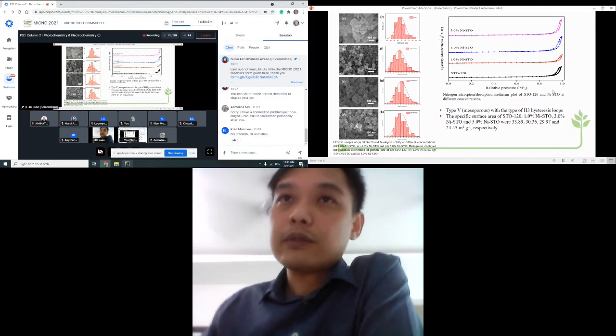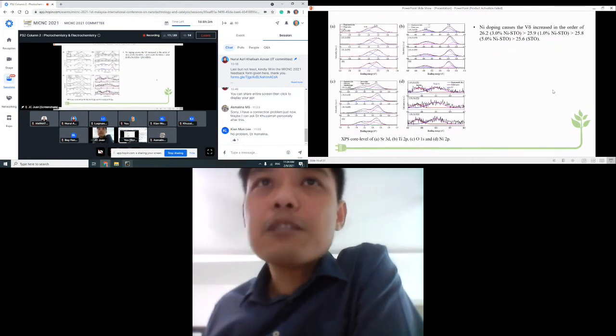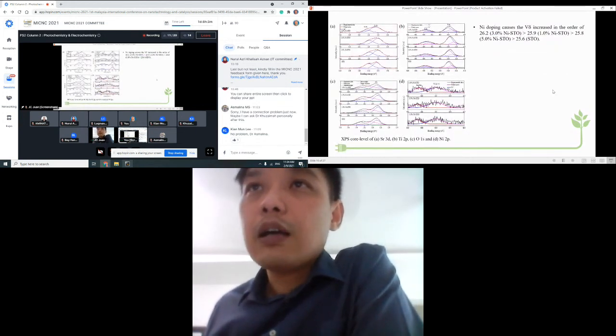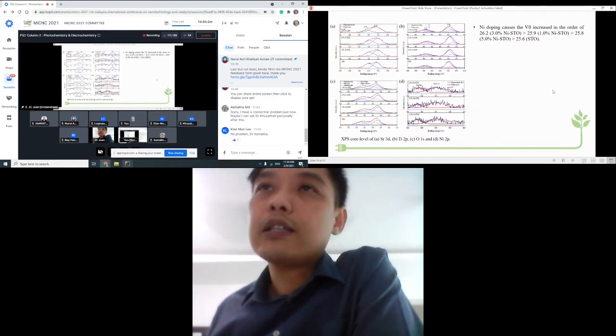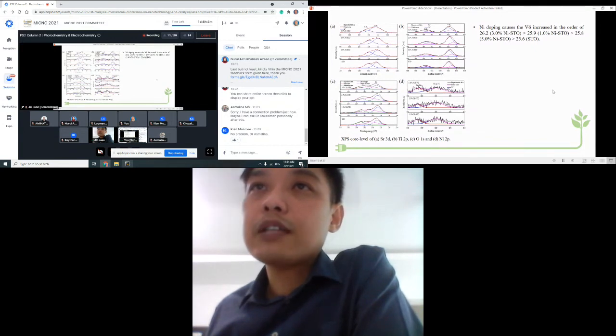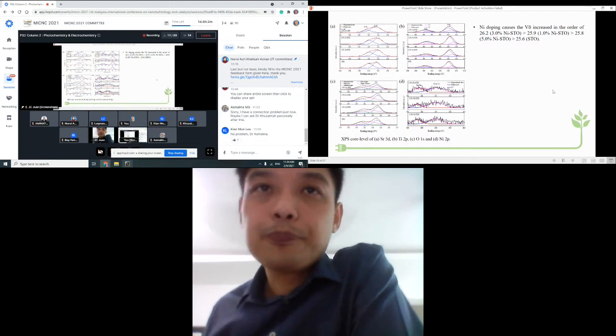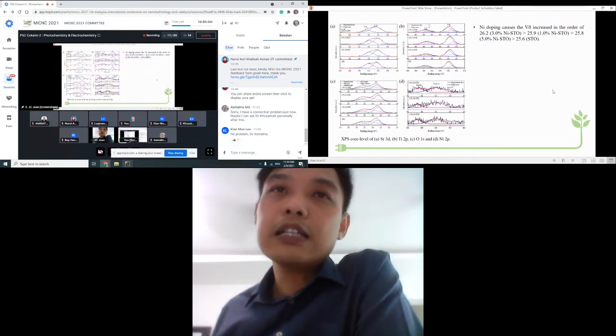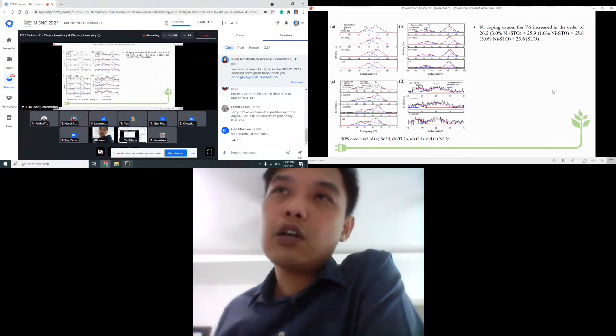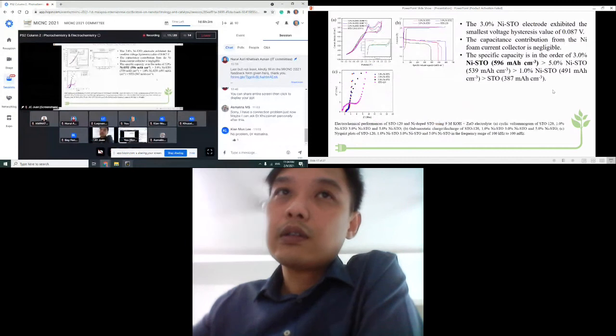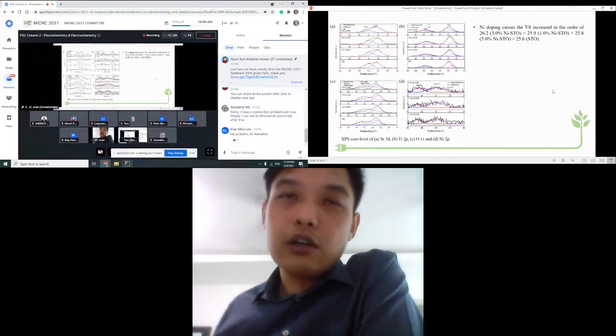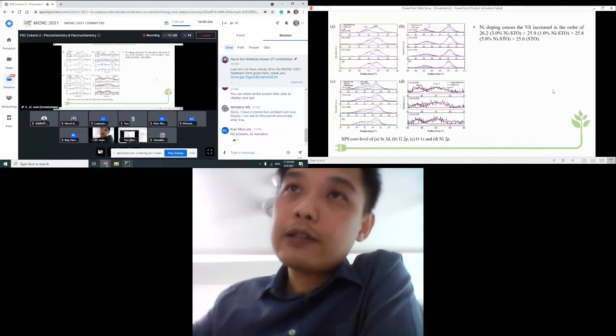From XPS, this is very important data. The nickel doping caused the oxygen vacancy to increase in the order of 3%, more than 1%, more than 5%, and more than STO itself. This shows that nickel is not only a dopant, but also induces this oxygen vacancy. So I will show you why this oxygen vacancy is very important later on.